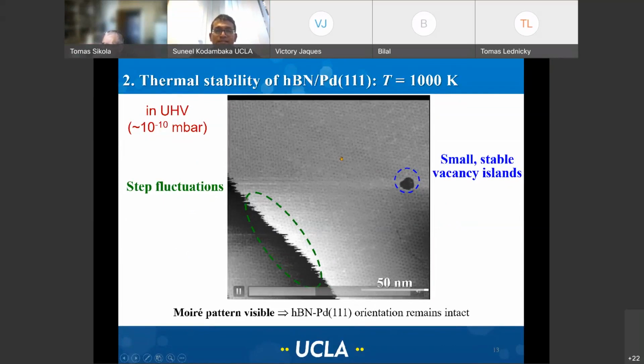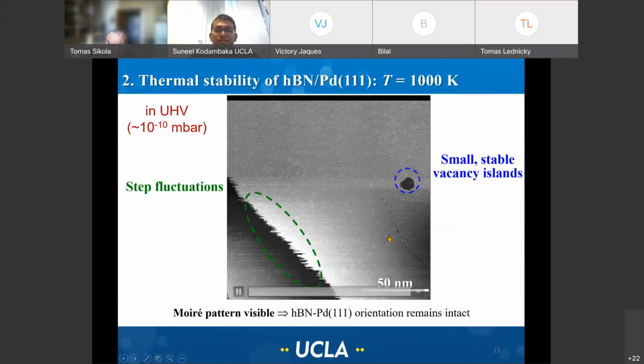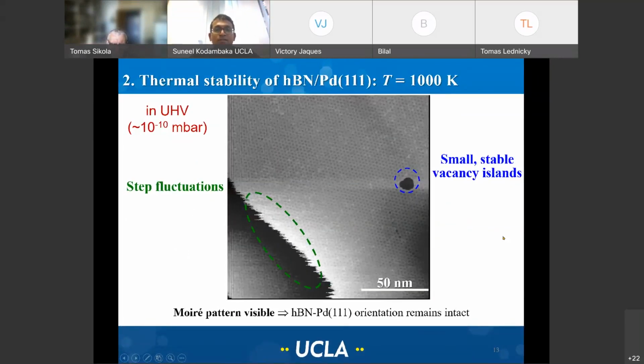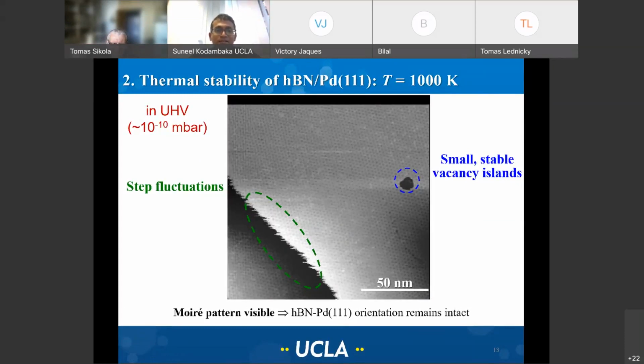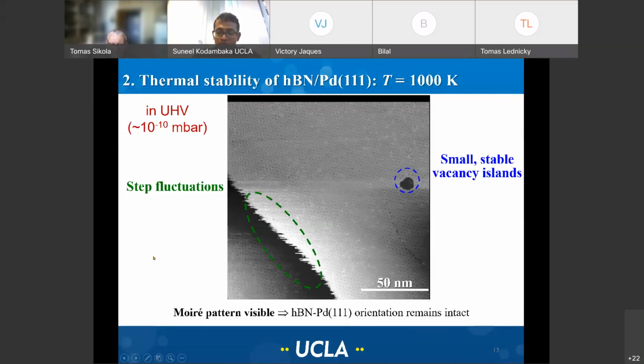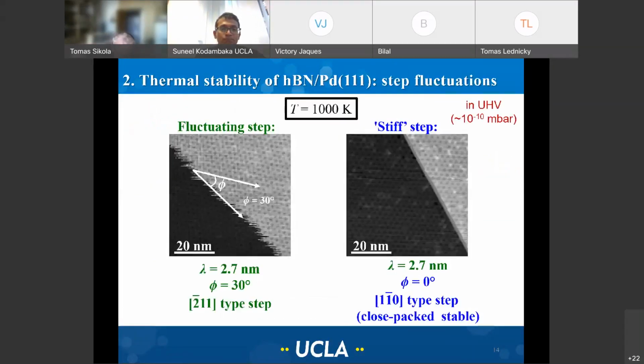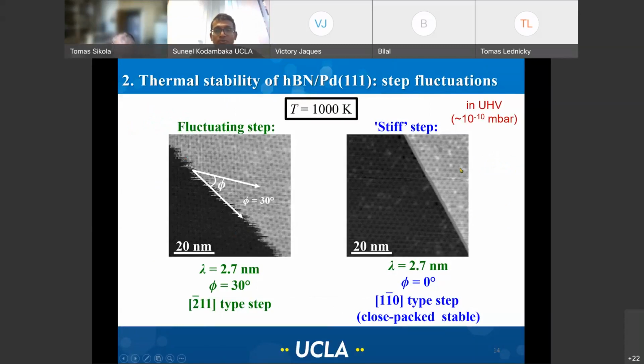One of the surprising things, at least for us, is that this moire pattern that you see remains unchanged, meaning the entire surface moves as in unison. So the layer on top sticks to the underlying surface as the underlying surface is fluctuating. And as you saw in the first portion of my talk, if you have a stiff step, you do not see any fluctuations, and that's the same case here. Whereas if you have a step with lower stiffness, you see these fluctuations. Both these images are obtained at the same temperature with the same monolayer boron nitride coverage. And so you see that the step stiffness plays a role.